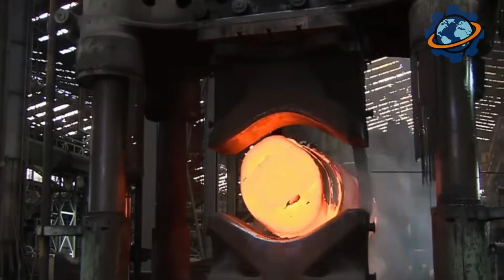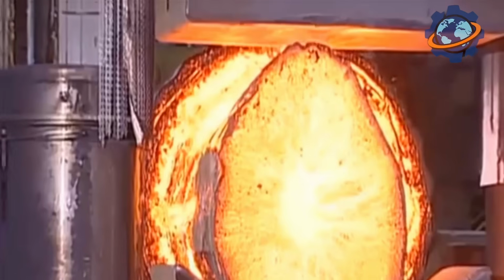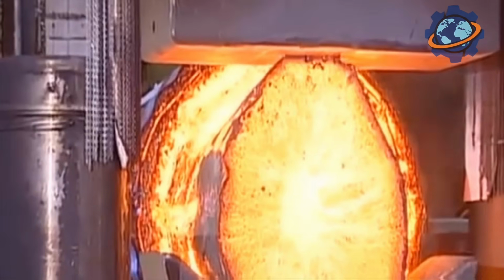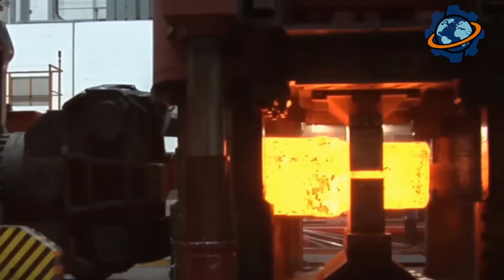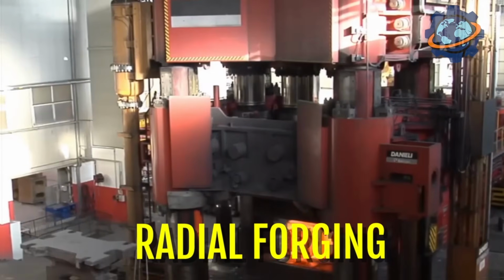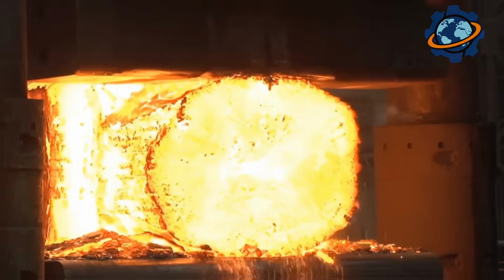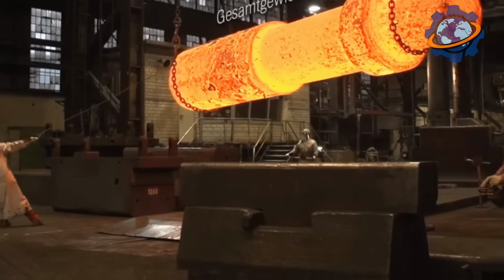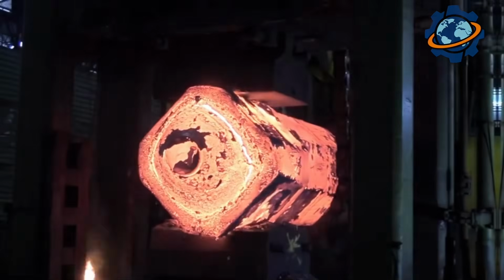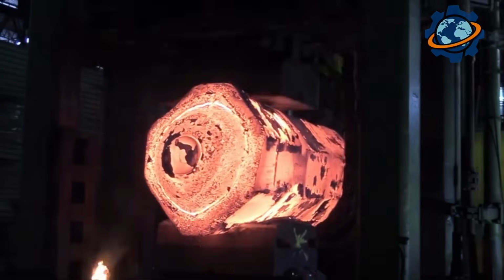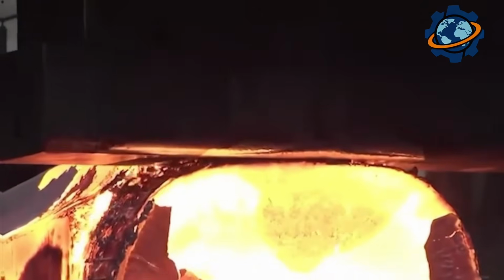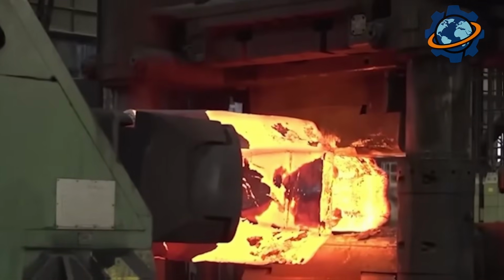The manipulator rotates the ingot a quarter turn, and the press strikes again. Then another rotation, another strike. This is called radial forging. The ingot is worked evenly from all sides. About 5 strikes happen per minute. Each strike sends out a fountain of sparks and flying scale. That's the oxidized layer of metal that cracks and flies off under pressure.